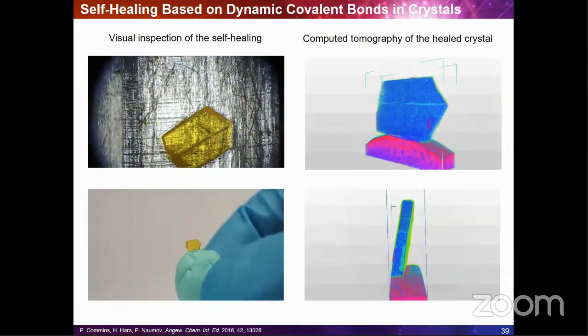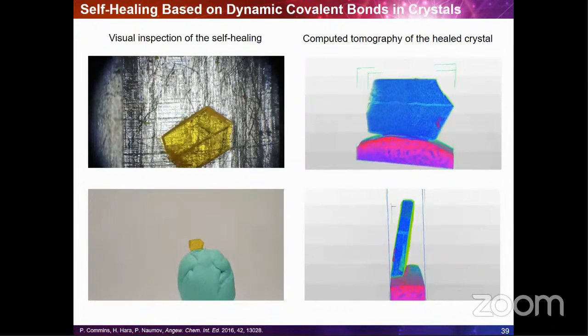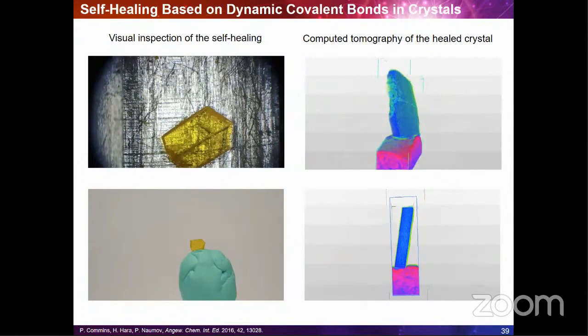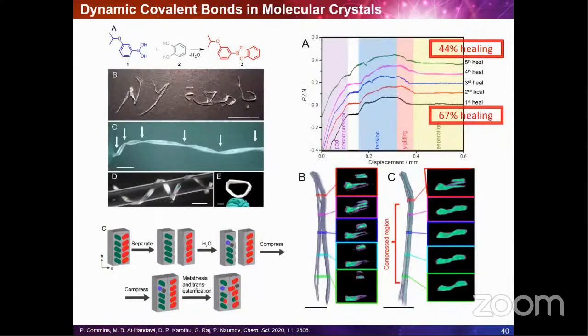And also we used computer tomography to look inside these crystals and look at their integrity and see whether the self-healing has occurred. Now we have improved this self-healing from about 7% to 67% by using a boronate chemistry. And basically, we can also do multiple cycles of self-healing. The self-healing decreases down to 44% after the 5th cycle. Okay, I'm just going to perhaps show the basic concept.